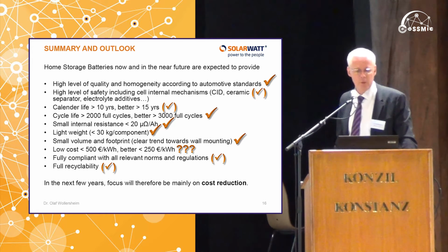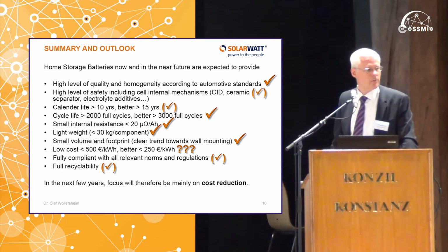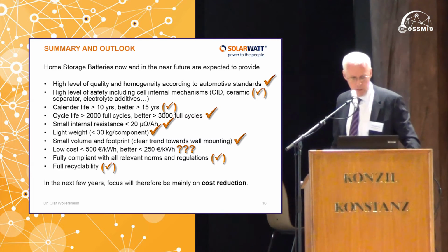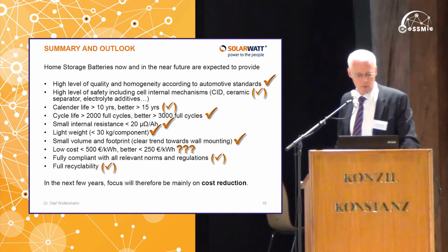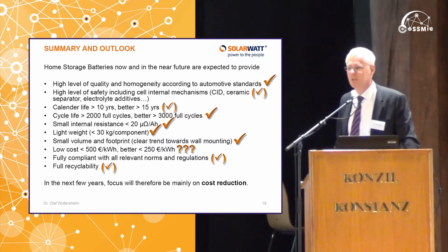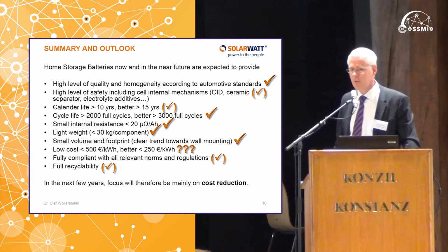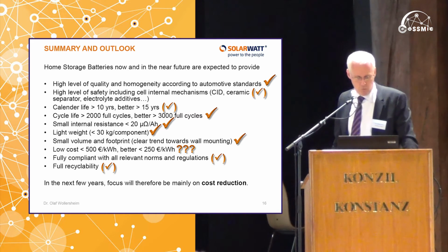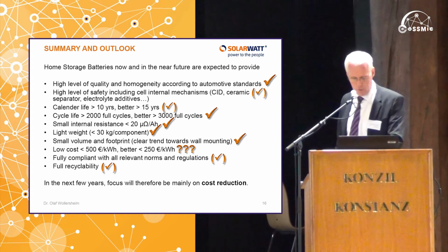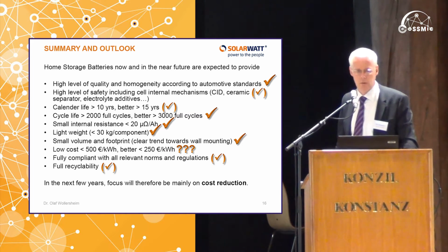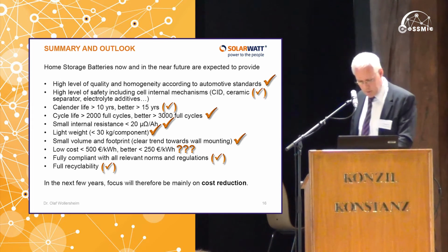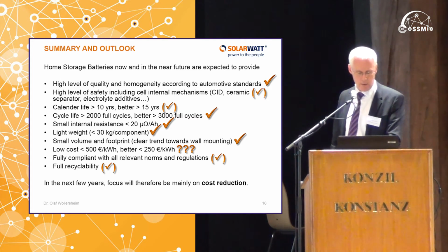It should be small in volume and footprint, and there is a clear trend towards wall mounting of these systems. It should be low cost, below 500 euro per kilowatt hour, better below 250 euro per kilowatt hour. This is really hard to achieve, and it's questionable whether it could be achieved, but this is a critical point. It should be fully compliant with all relevant norms and regulations, of course, and it should be fully recyclable, which is not given with some of the systems that we see today on the market. So, as you can see, almost all of these requirements are fulfilled, or at least there are some systems that can fulfill them. The big question mark is price.